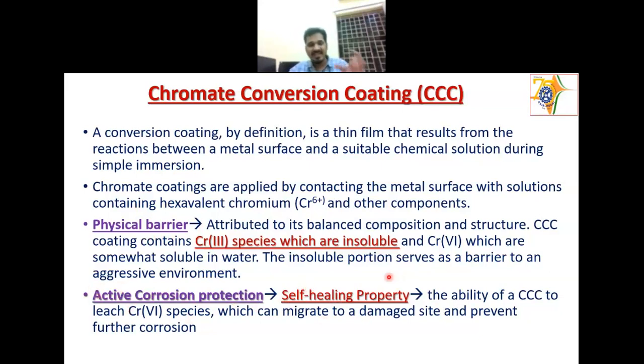So that Cr6+ can actually leach in the coating and go to the area with the damaged site, and it prevents further corrosion there by making a film there. So this is one of the important properties, the self-healing property of this chromate layer, when it is acting as a conversion coating or when you add zinc chromate or strontium chromate as a pigment in the coating. So this is one of the most important things for the chromate conversion coating.